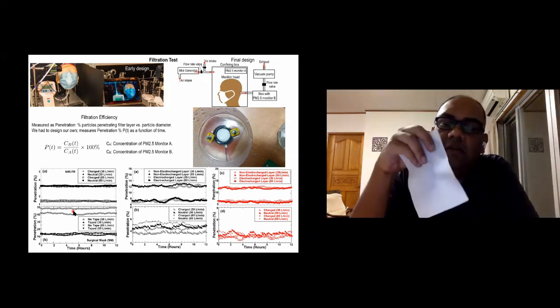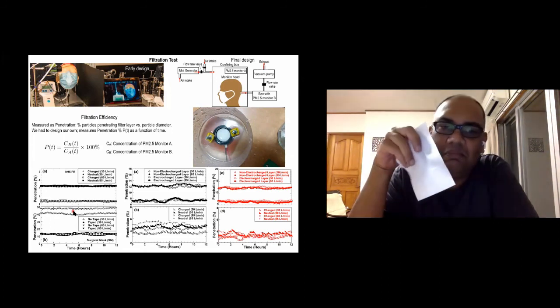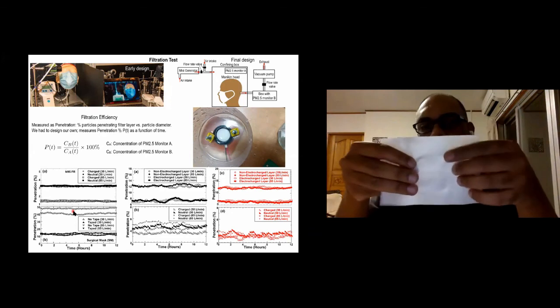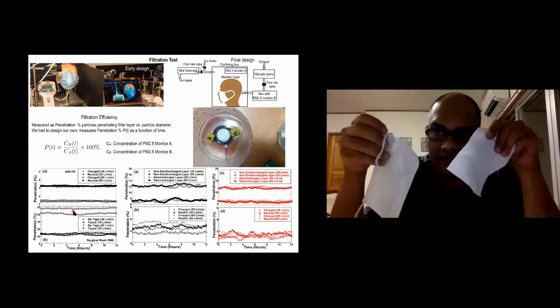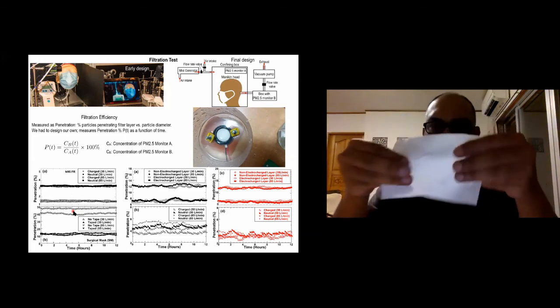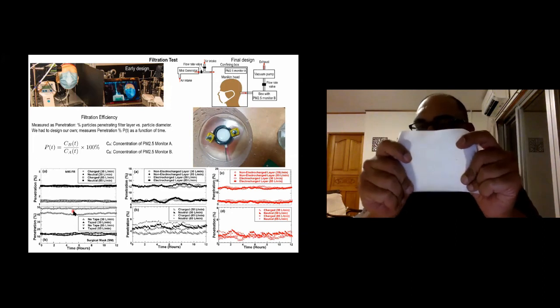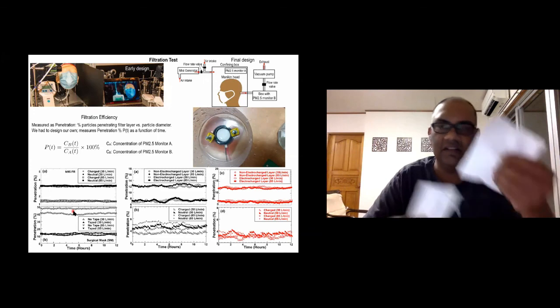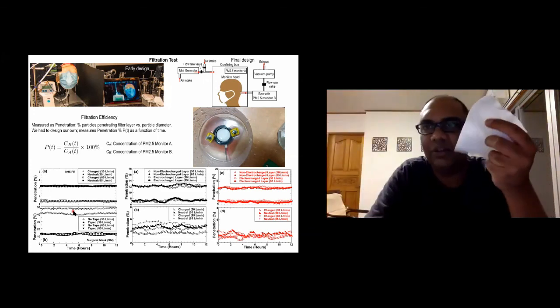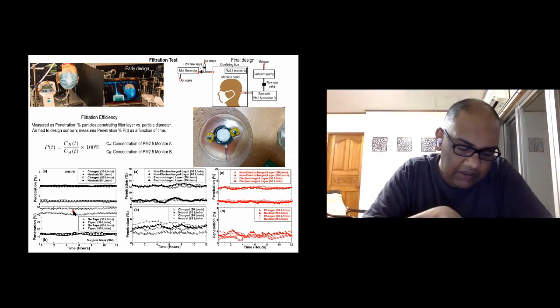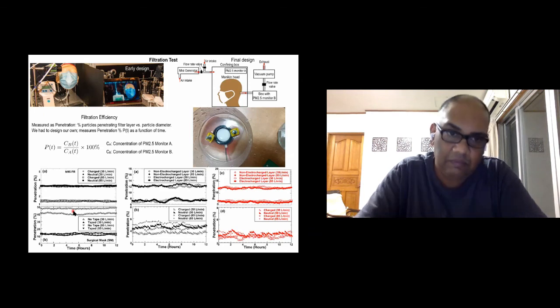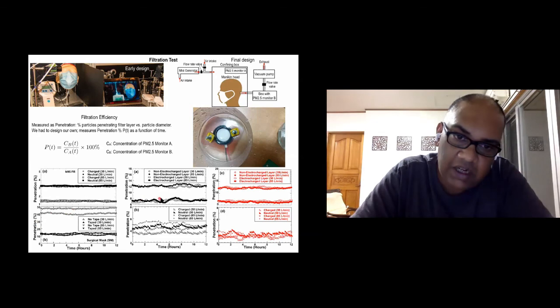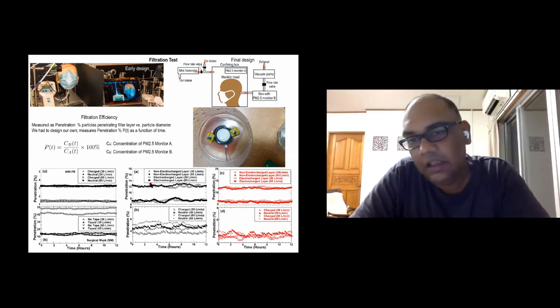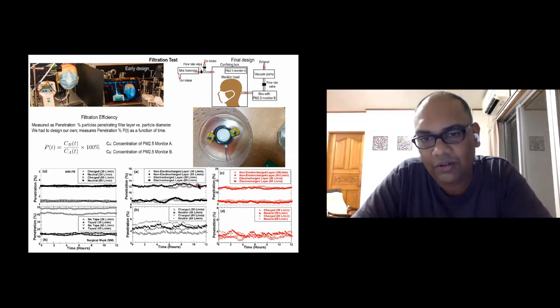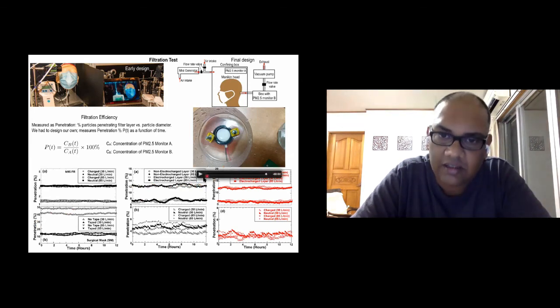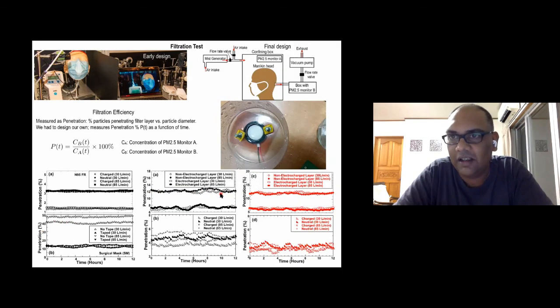So these are not washable. I did try washing them, and it's not that it comes apart. I tried washing the commercial surgical mask, and this holds pretty well. But the ones I made with the cotton candy machine would degrade more easily, and I suspect that is because there is some bonding going on in these kinds of materials that I don't have access to. About particles passing through, I don't have any good ideas. From the penetration tests, they were looking good for about 12 hours. If you look at this plot, what I haven't seen is that at some point the penetration should start rising because there is no more filtration efficacy left.